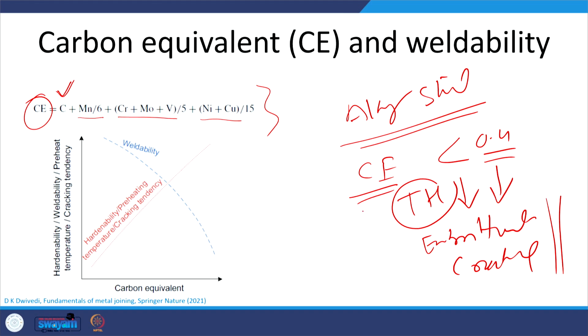If we have a higher carbon equivalent, then the weldability will be less. If we see the carbon equivalent on the x axis, when the carbon equivalent is low, the weldability is very high. If we go for a higher carbon equivalent, then the weldability keeps on decreasing. Why? Because of increased hardenability and increased preheat requirement to avoid cracking and embrittlement. Therefore, the weldability keeps on decreasing, because we need extra care and extra precautions to develop a sound weld joint of high carbon equivalent ferrous metals.